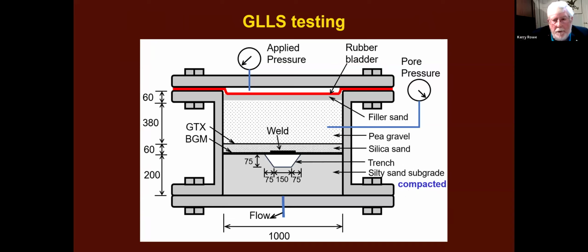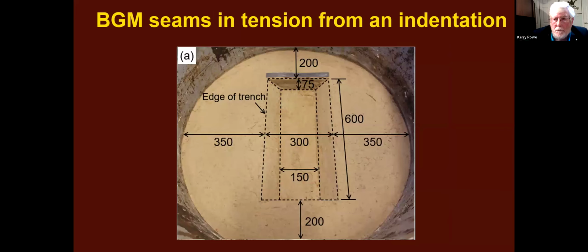So those are all in isolation. So we thought, let's try simulating what may happen in the field. We've got an indentation 75 millimeters deep, 150 millimeters wide at the bottom. It's in a sand. We put a BGM with a weld on top of it. We put a geotextile, we put some sand on top of that, then a geotextile, then some gravel. And we can apply loads. We can also apply water pressures in our geosynthetic liner longevity simulators. So here's what it looks like within the cell. And you can see the indentation is 600 millimeters long.